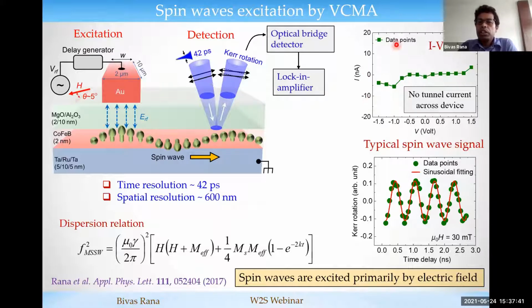If you see the DC IV characteristic of this junction, you can see that when we apply the gate voltage up to plus or minus 1.4 volts, the current flowing across the junction is almost zero. So there is no current across the junction. That means the spin wave which we are exciting is purely excited by the electric field induced method, not by the charge current induced method.